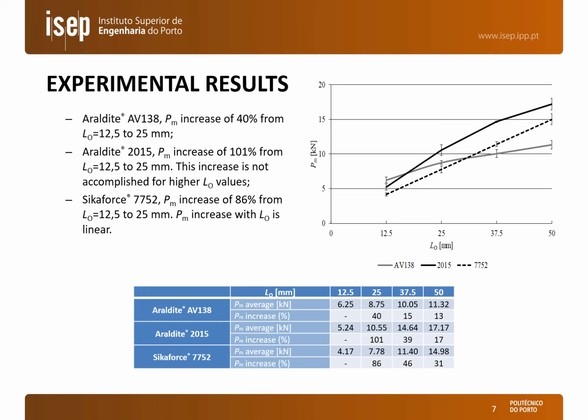In the table below we can see the percentile improvements between consecutive overlap lengths for each one of the 3 adhesives, and we can see that the maximum increase was obtained for the Sikaforce 7752, which achieved improvements of 86%, 46% and 31% between consecutive overlap lengths, and this is because of the fact that this adhesive has a high ductility.